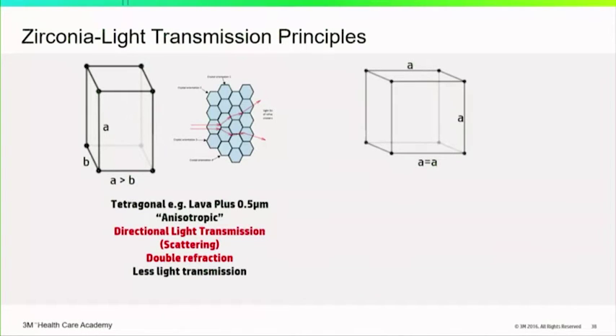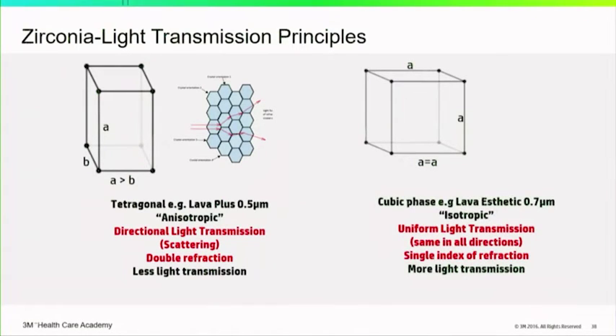Cubic zirconia, on the other hand, in its pure form, in the cubic phase, as in the case with Lava Esthetic, the crystal size has actually been increased. And owing to the fact that a cube, or a square, if you will, has equal sides, you'll get a uniform light transmission, and there are fewer boundaries owing to the shape of the crystal. By accommodating and mixing the correct proportion of the cubic phase with the tetragonal phase, the 3M engineers have been able to achieve a level of aesthetics which frankly rivals anything that I have seen, particularly as it relates to what a lot of doctors like to use today, which is lithium disilicate. So we're going to get a lot more light transmission.